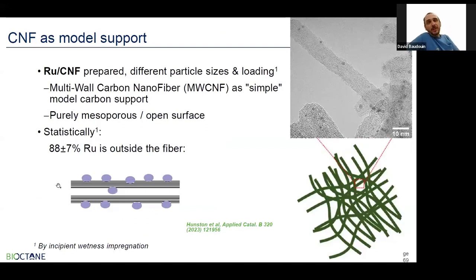In the rest of the presentation, I will focus on ruthenium supported on carbon nanofibers. Often activated carbon is used because it is much cheaper. It also has a high surface area, but unfortunately, activated carbon is mostly micropores, and these are actually completely useless under these conditions because they get filled very easily, and ruthenium is mostly not present in the micropores, but in the mesopores of the activated carbon. So carbon nanofiber is used in most of our scientific studies, in order to largely simplify the study of the spent catalyst.